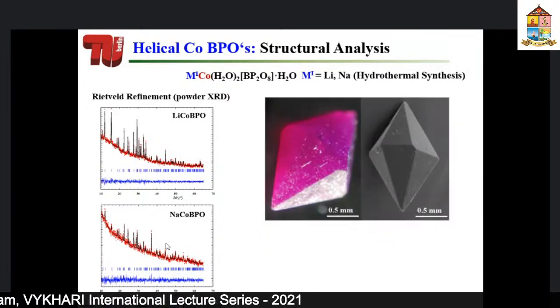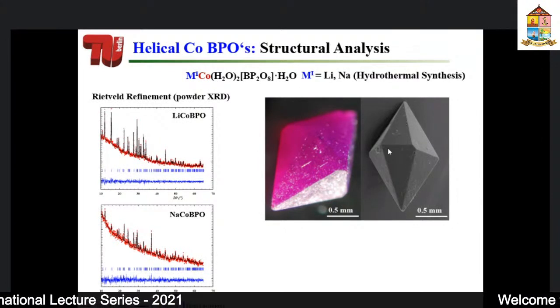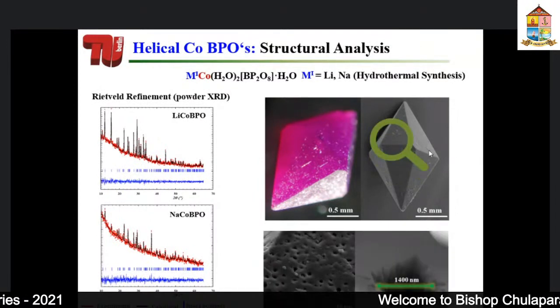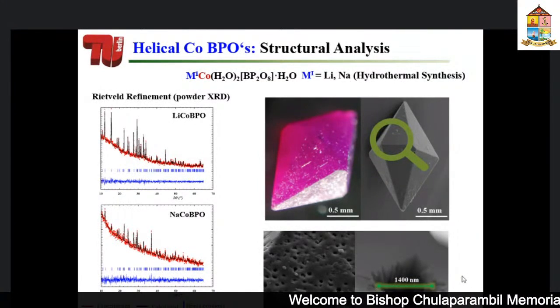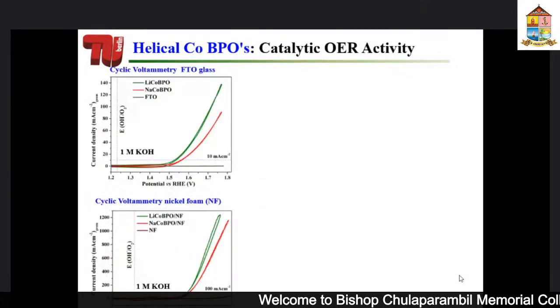Okay, then we checked the morphology of the material. This is the optical microscopic picture. As you could see, they are nice pinkish hexagonal bipyramids. And this is the scanning electron microscope image, where you could see even at, let's say, 0.5 millimeter sized hexagonal bipyramids. And interestingly, if you zoom in here, you would see that they have pores. This is the high resolution image, and you could see that you have a pore size of almost 1400 nanometer. Okay, as I told you before, we deposited this material, how to deposit this material on the electrode.